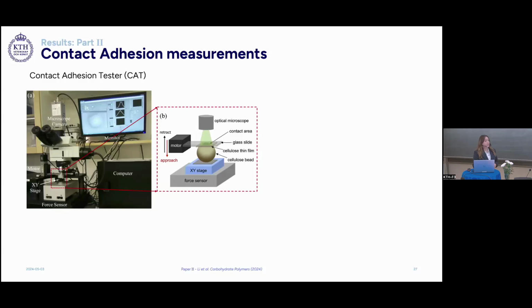Contact adhesion measurements were performed using a custom-built contact adhesion tester, using a cellulose bead and a cellulose thin film as model materials. This measurement is performed by placing a dry cellulose bead on a force sensor and gluing a cellulose film on a glass slide, which is connected to a translation stage. The two materials are brought into contact by moving the translation stage downwards until reaching a set load or a trigger value. Then the two surfaces are separated by retracting the translation stage upwards until separation of the two materials.